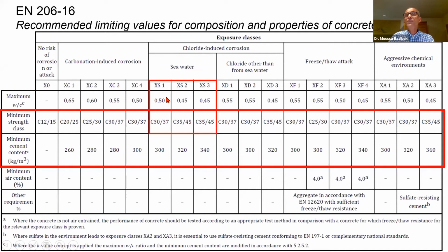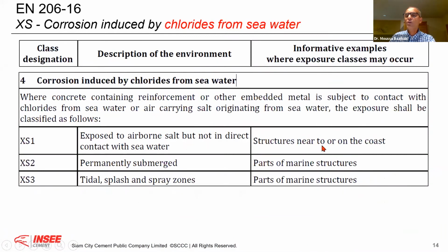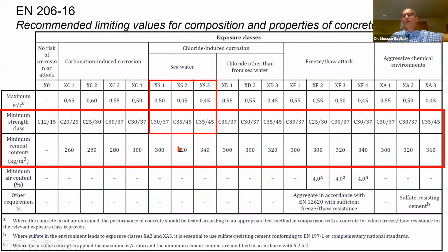Therefore, if I take, for example, buildings in Colombo, minimum those buildings should be XS1. Because you remember we say XS1 is a structure near or on the coast, exposed to airborne salt, but not in direct contact with seawater. Even if we are at 25 kilometers from the coast, therefore I will say Colombo and greater Colombo, normally all the concrete needs to be designed with minimum XS1. This means the water cement ratio should not be above 0.5. This is one condition. And we are talking about strengths. Therefore, you cannot design with less than 37 megapascal.